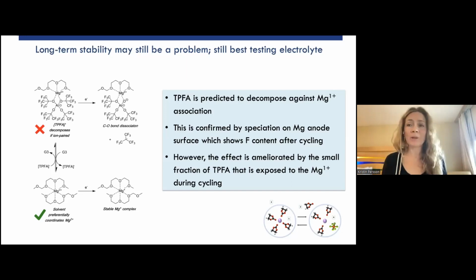So you will have a very small minority species that keeps being chewed up every single cycle, which is where the Coulombic inefficiency comes from. And indeed, we see that there is fluorine content after cycling on magnesium metal anode surfaces, which corroborates the fact that there is a slight amount of instability. That being the case, when we test high voltage cathodes at Berkeley, this is still our go-to electrolyte. But as far as I know, it's still not available commercially. You have to make it yourself, which makes it a little bit difficult.